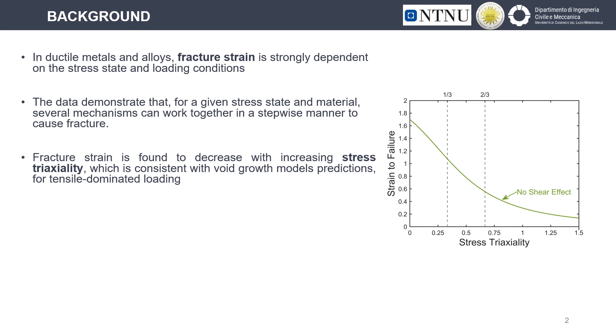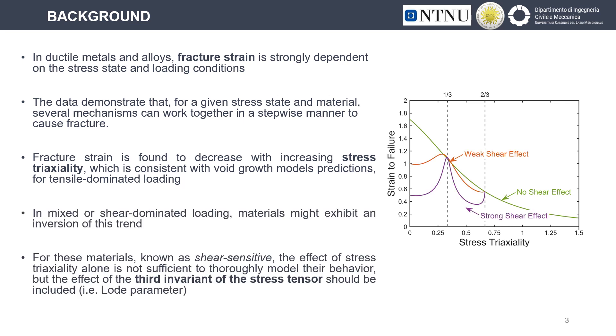This is true for tensile-dominated loadings, but in the case of mixed or shear-dominated loadings, materials may exhibit different behaviors depending on their shear sensitivity. These results highlighted how stress triaxiality alone is not enough to thoroughly model the behavior of shear-sensitive materials, and other parameters depending on the third invariant of the stress tensor should be taken into consideration.